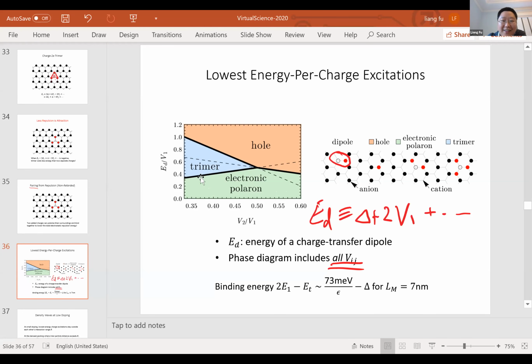So we see that in these different parameter ranges, what is shown here are the lowest energy per charge excitations. We compare the energy cost of creating a single hole with half of the energy cost of creating a charge 2e trimer. And we see that in some parameter range, trimers cost less energy per charge compared to a single hole. Remember that in this whole system, the charge exists in the form of holes, right? So this is what we mean.